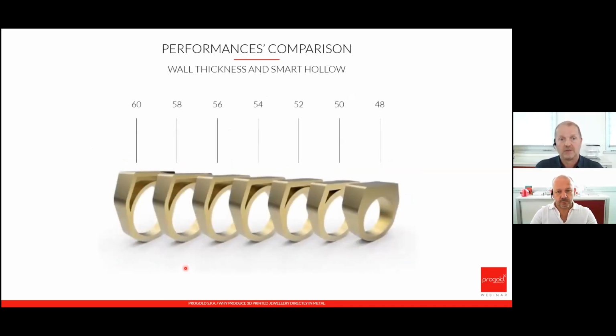By wall thickness, you can also control another thing. In fact, SLM allows you to maintain the same weight when the size of your part changes. Here we have some different rings, an example of rings from size 48 to size 60. You understood that you can change the wall thickness of your parts and maintain the same weight.